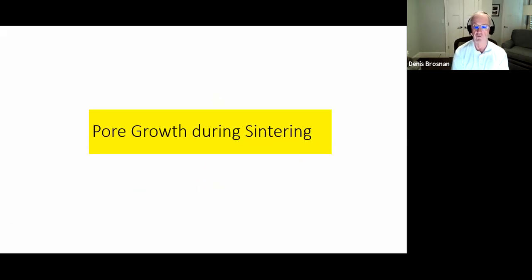So, as I mentioned, pores grow during sintering. The small pores grow at any rate. If you have macro pores, they may diminish, at least in extent, to some degree during the consolidation during sintering. But pore growth during sintering is a way to figure out at what temperature somebody made their product, in addition to thermal dilatometry. But pore growth and sintering of higher purity ceramics is the way that I've done that. So that's why we need to know about pore size distribution, since it changes.